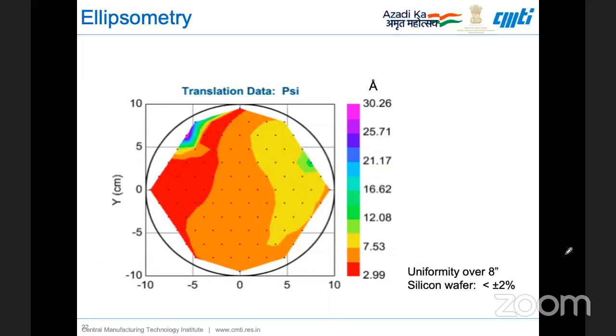So just to show how good our coating is, this is about 30 angstroms, that's 3 nanometers. At about close to 500 nanometers, or to be more precise, 485 nanometers, our variation is just about 30 angstroms, or 3 nanometers. So it's as low as that, and that is even less than a percent, I can say. For all wafer sites, we say plus or minus less than 2% is the uniformity, but it's much better than that.